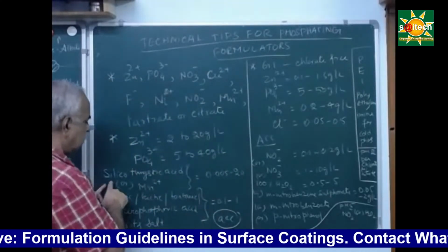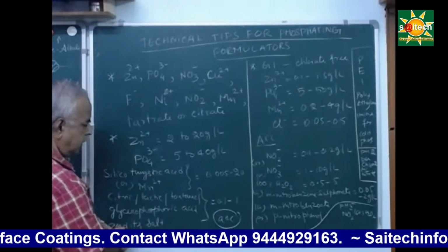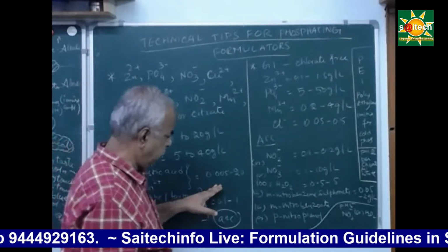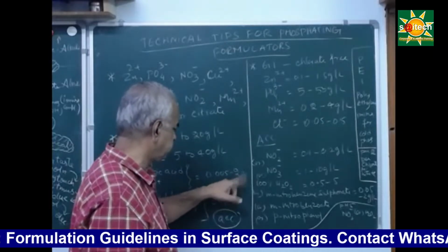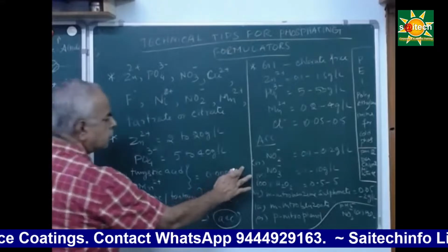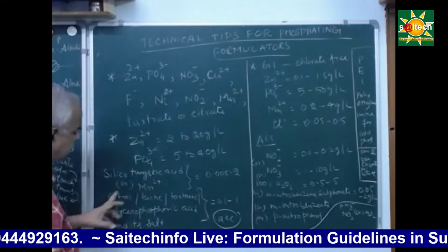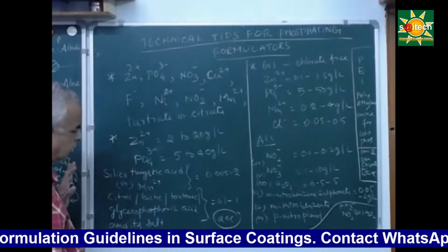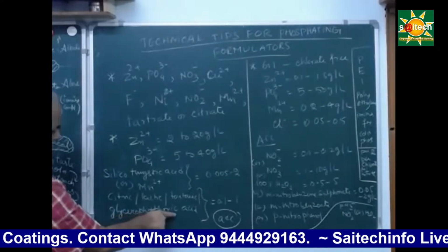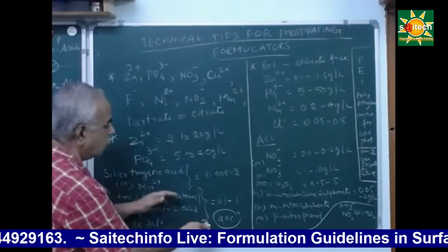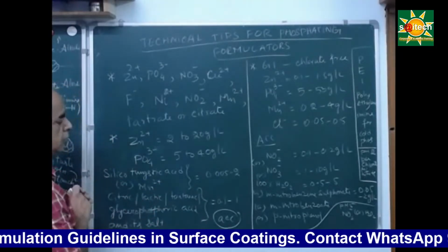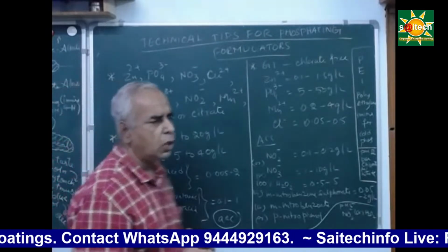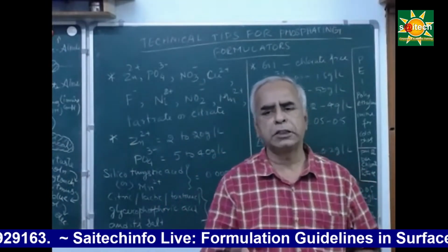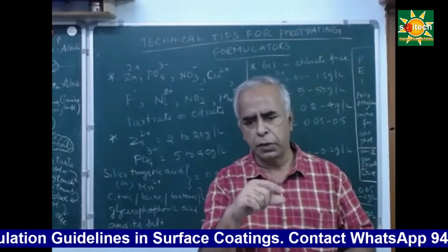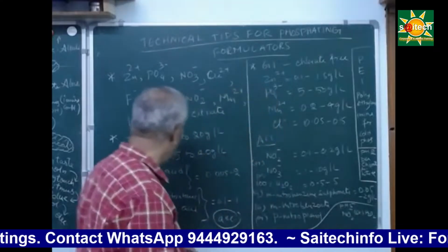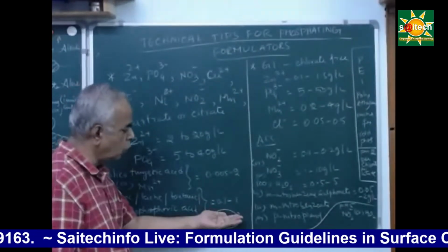Then silicotungstic acid. This is one of the accelerators actually, and here you can have the maximum dosage of 0.05 to 2. And you have manganese, which is 2 grams per liter. Then citric or lactic or tartaric acids, and glycerophosphoric acid and its salt. You cannot take all together. You have to consider only one accelerator, one oxidizer. Oxidizer is nothing but an oxidizing agent that increases the speed of the reaction, and especially this nitrite tunes the fine crystal nature of the zinc phosphate. I have noted down the maximum load also, 0.1 to 1 gram per liter.